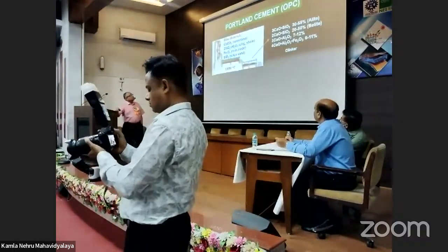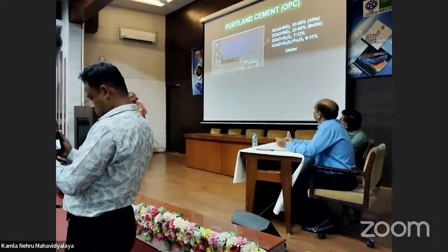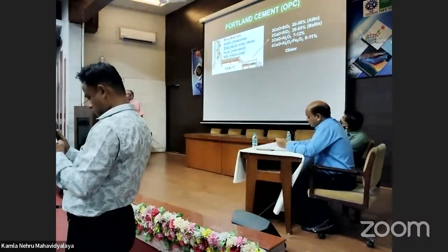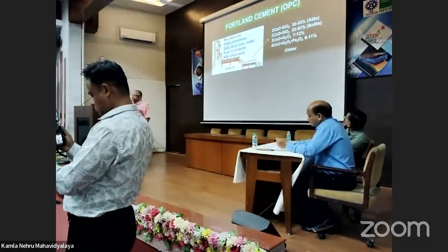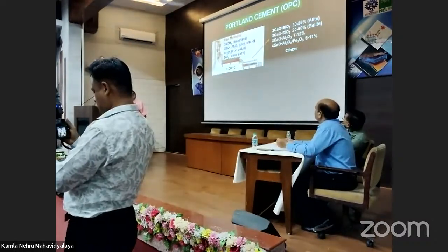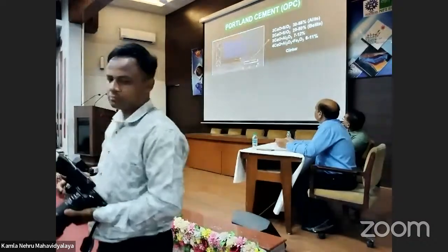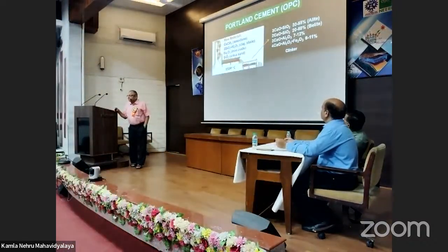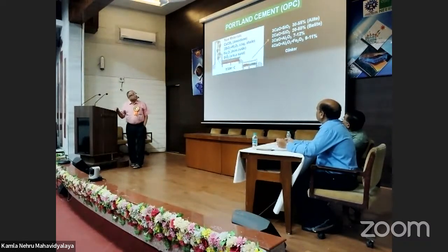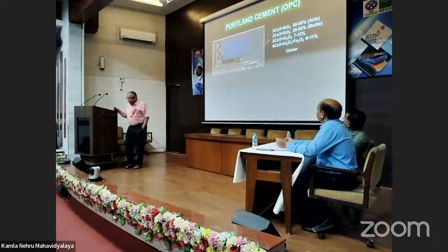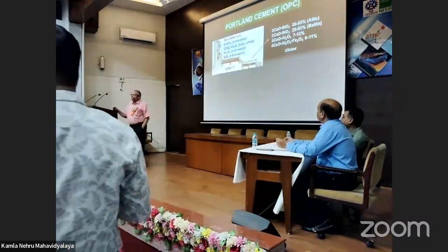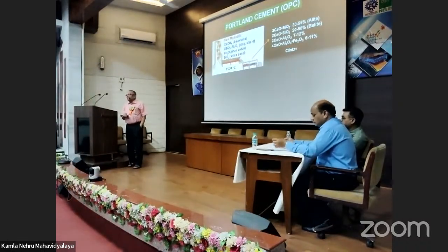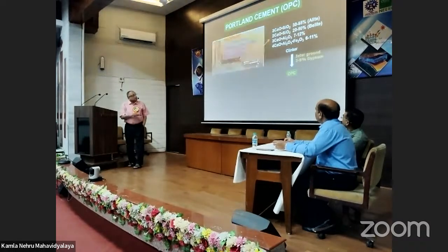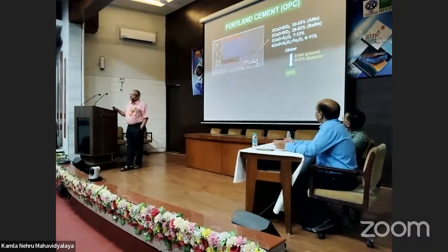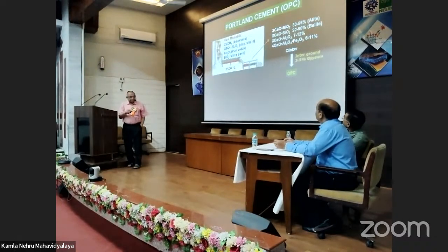A simple picture is here. We take the raw material, different constituents are there. We mix them in appropriate amounts and fire at around 1500 degrees centigrade. Then we get a mixture of different components known as clinker. The components are tricalcium silicate, about 30 to 55%, dicalcium silicate, 20%, tricalcium aluminate, 7 to 12%, tetracalcium aluminoferrite, 6 to 11%. This composition varies from raw material to raw material, from industry to industry. Clinker is a very hard material, and when it is interground with 3 to 5% gypsum, that is calcium sulfate dihydrate, Portland cement is formed.